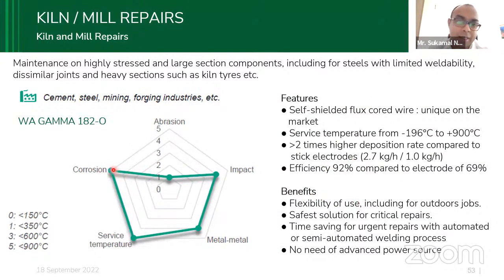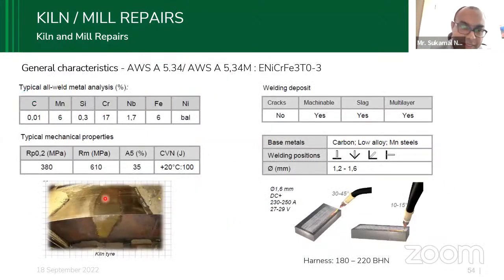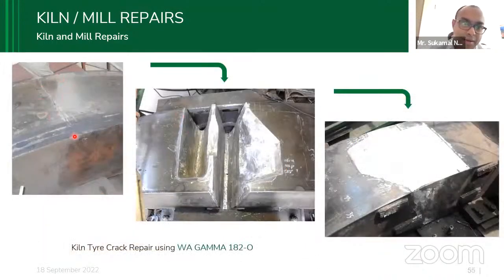It all depends on, like here, the corrosion was very strong, service temperature was quite high, the metal abrasion was quite high, impact was also moderate. So this basically determines how to select the right composition or method for this repair. Here it is very interesting, you can see it was completely worn out, and we removed it, rebuilt it and reused it. Okay, so this was the actual picture of the component, where from this crack we removed this amount of material. Then from here we came here, we excavated it, and then we rebuilt it and sent it back for operation.